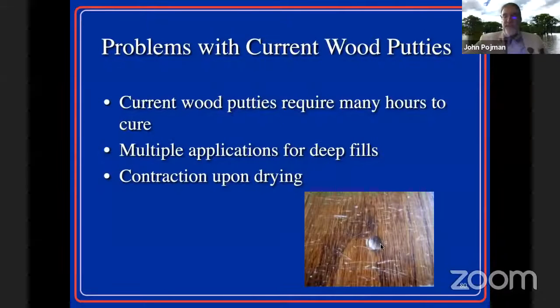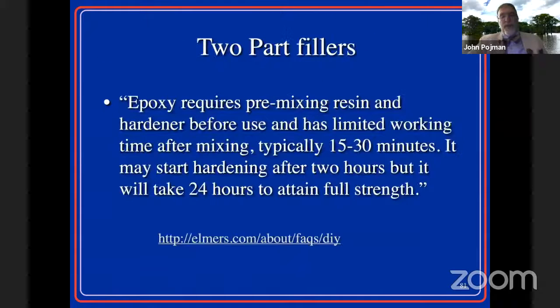So this is one problem with some of these. When you have a little hole that you want to repair in the wood, some systems shrink when they harden. So you're not left with a uniform surface. Another way people do it is with epoxies. Some of these you have to mix. You have about 15 minutes to work and they still take about 24 hours to get full strength.